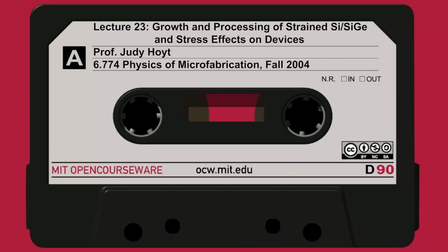Its lattice parameter in the X and Y plane is about 1.5% bigger than it would be in normal silicon. That's a huge amount, to take a silicon crystal lattice and stretch it by 1.5%. As a result, when you stretch it in the X and Y, it actually compresses a little bit in Z. So we call this particular configuration uniform biaxial tensile stress. It's biaxial because it's being pulled in X and Y, and tensile. So this is the classic way that people have introduced strain and made MOSFETs, and they've looked at the mobility as a function of the amount of the strain.